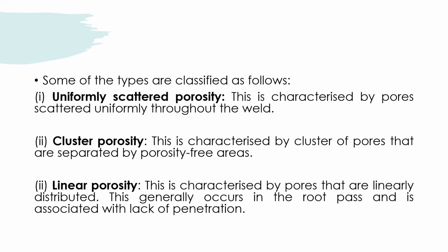So what is uniformly scattered porosity? This is characterized by pores scattered uniformly throughout the weld. What is cluster porosity? This is characterized by clusters of pores that are separated by porosity-free areas. Linear porosity is characterized by pores that are linearly distributed. This generally occurs in the root pass and is associated with lack of penetration.